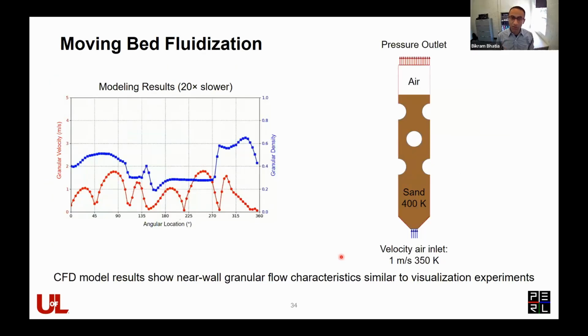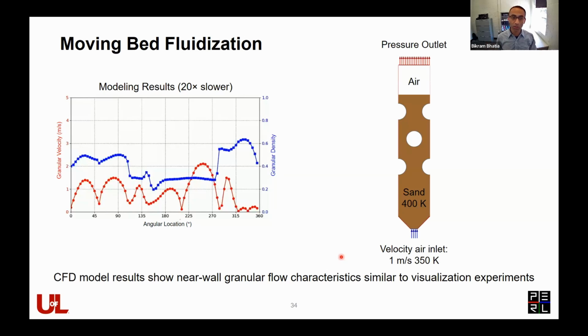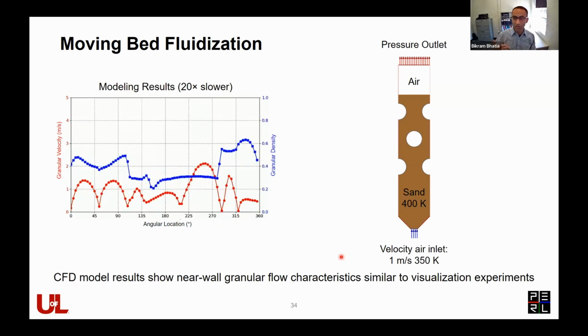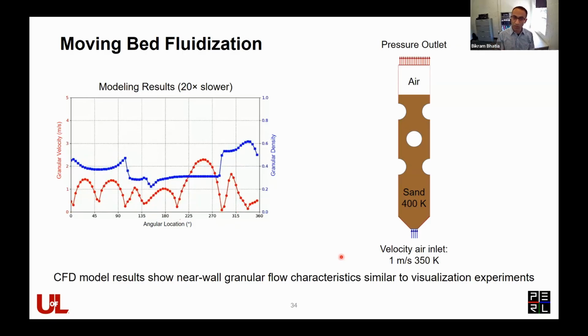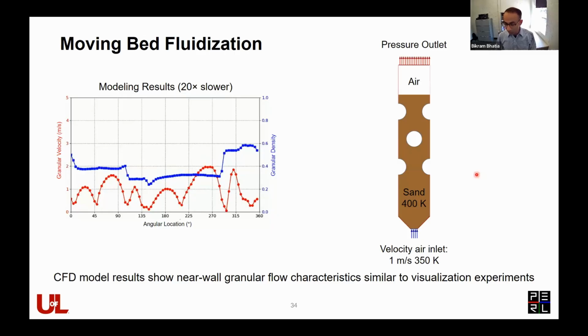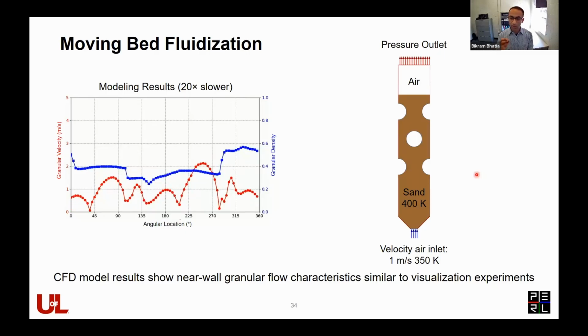But we looked at, as a first step, a very simple volume of fluid model, which also gave us a granular velocity and granular density, which had magnitudes on the same order as the experiment, but it was a much simplified model. We could run it for a wide variety of parameters based on the experiments, and we also validated these results.